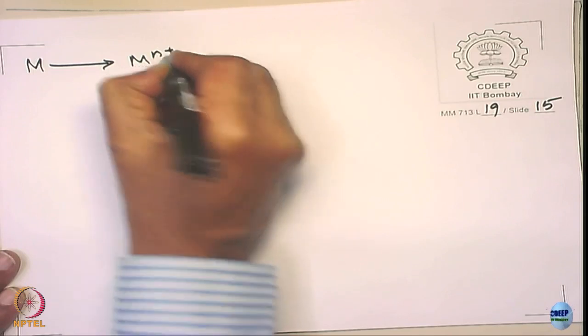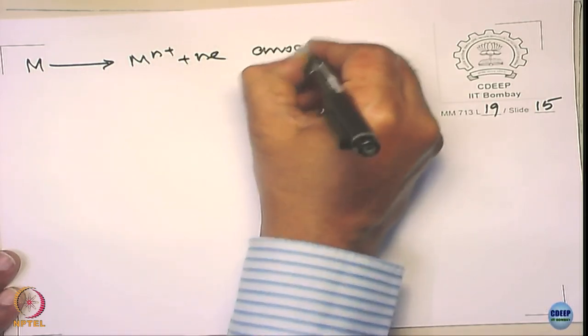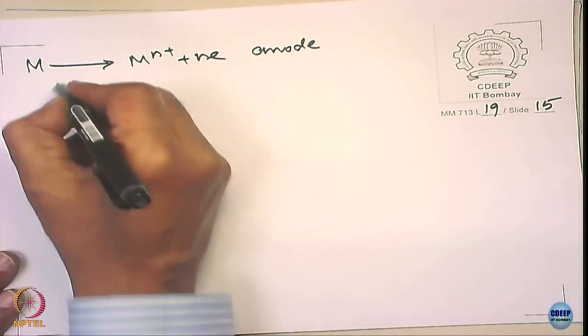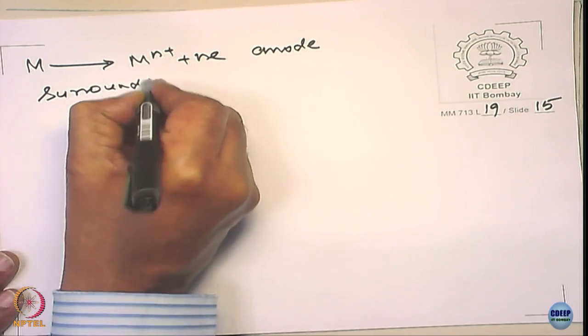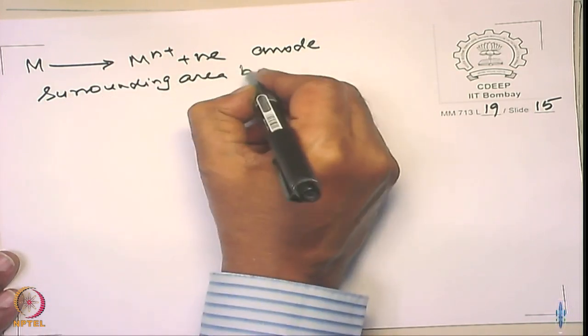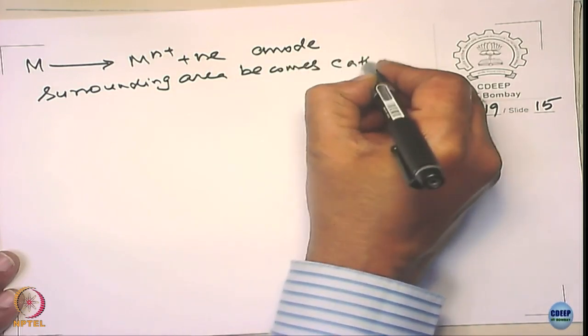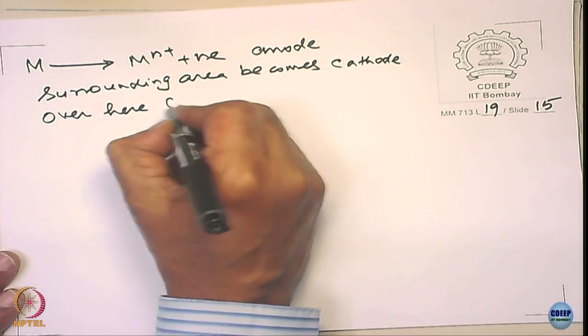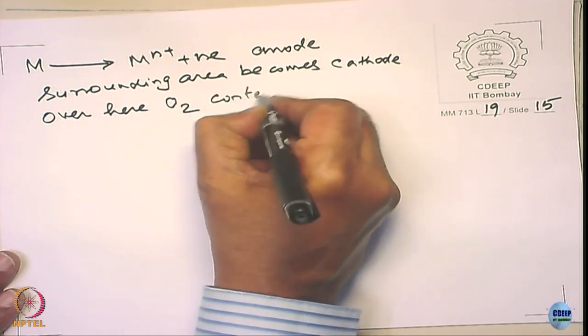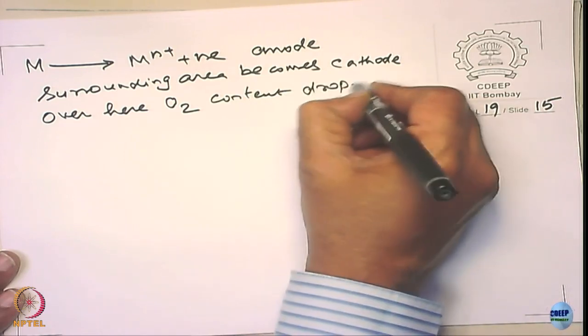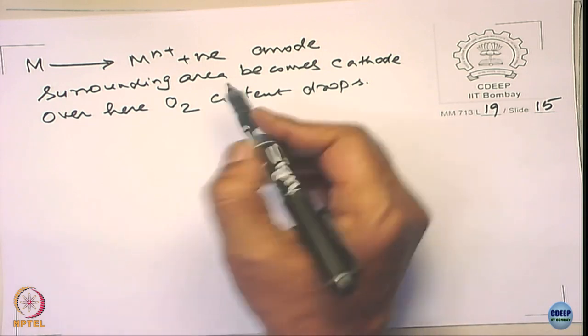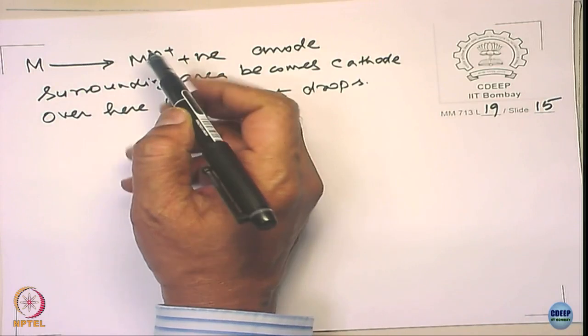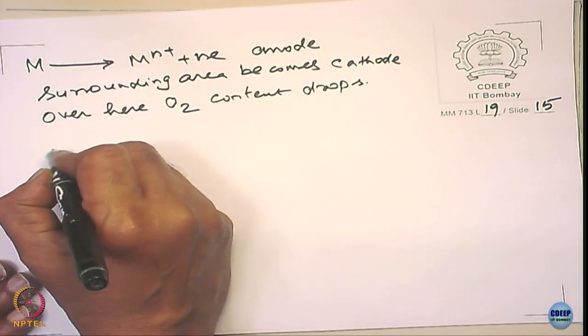It will generate various cations. For example, if M goes into solution as M^n+ plus an electron, this becomes an anode. Now, the surrounding area becomes cathode. And over here, oxygen content drops. Why does the oxygen content drop? Because it's covered with a corrosion product. Now you have these metal ions generated here, right? And these metal ions, when they're generated,